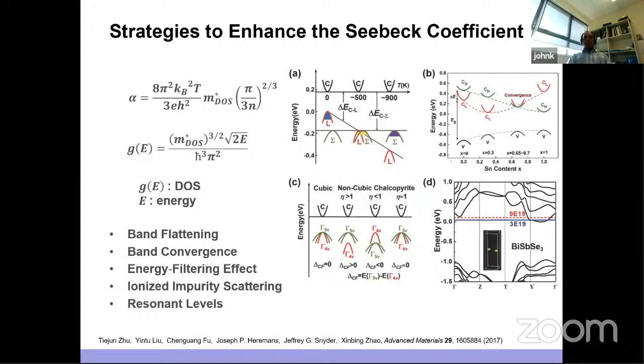Some of the strategies used in recent days is to enhance the Seebeck coefficient. You can see diagram A, which gives a schematic diagram of temperature-induced band convergence, in this case lead telluride selenide. And B tells you composition-induced band convergence, where you can see the pseudo cubic structure to tetragonal structure. Then D gives you structural transition-induced band convergence. So there's quite a bit of theoretical work looking at the band flattening and band convergence effect. The other one is the energy filtering effect, which is related to effective carrier mass, concentrations and impurity scattering as well. So that's the basic physics, which can help us understand what mechanism drives the material properties.